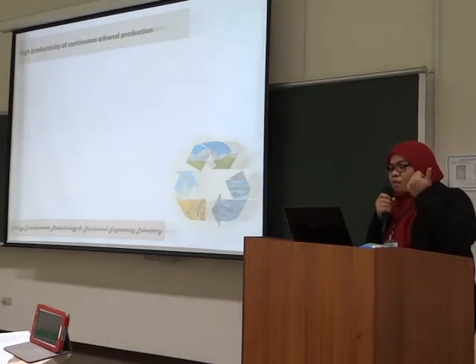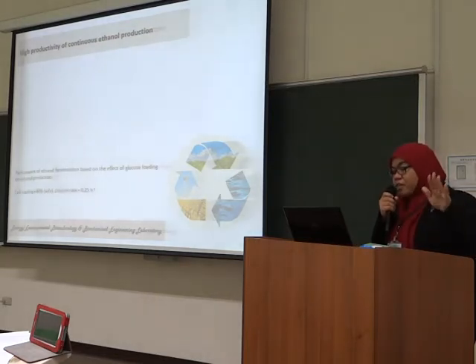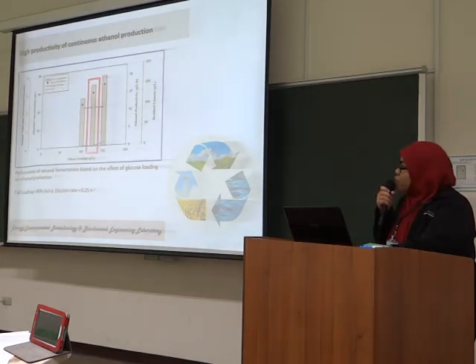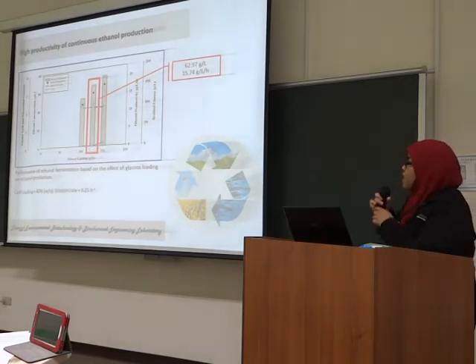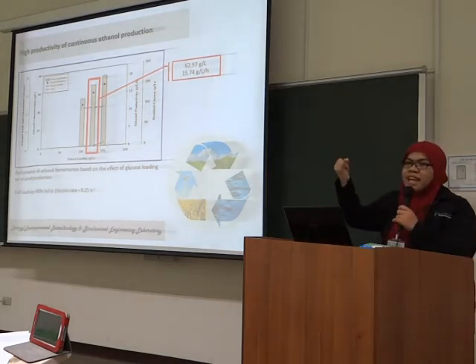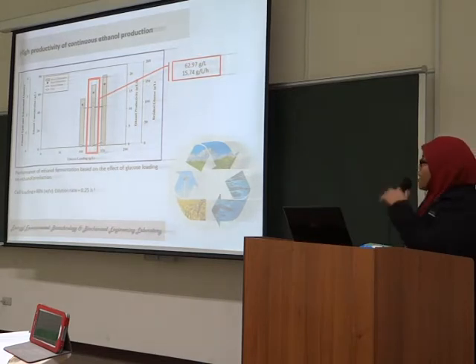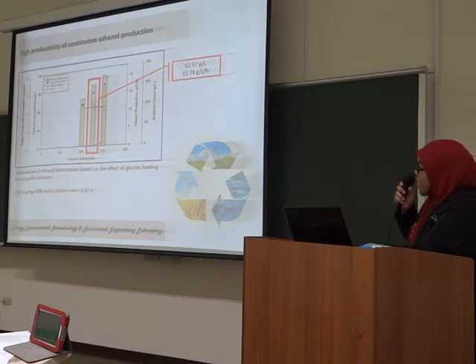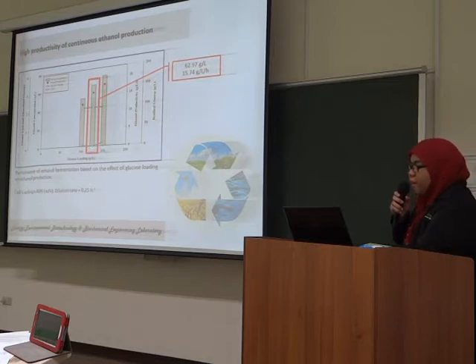And after we got the optimal cell loading and also the optimal HRT, I tried to increase the initial glucose loading from 100 gram per liter to 125 gram per liter and 150 gram per liter. And in here, first we consider the ethanol productivity, and second we consider the residual glucose. So I chose 125 gram per liter of initial glucose loading as the optimum condition, with the ethanol production about 62.97 gram per liter and the ethanol productivity around 15.74 gram per liter per hour. I think it should be good enough for the ethanol productivity.